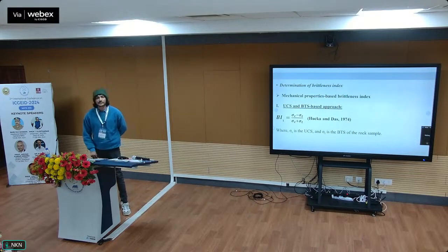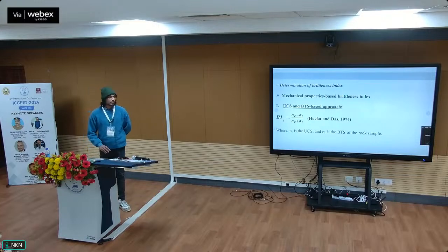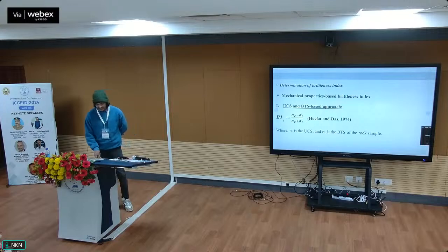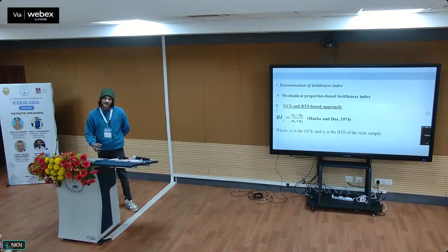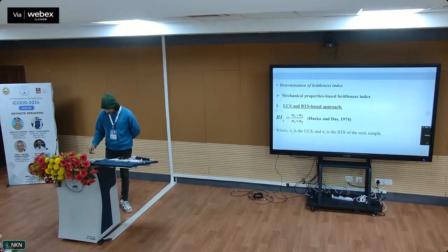We have actually used 6 brittleness indices, and those were broadly separated as mineral-based indices and mechanical-based indices. This is the UCS and BTS-based approach. Basically, we have calculated the uniaxial compressive strength and tensile strength of the samples. Then the ratio of both gives us the brittleness index, because if a sample's UCS is high, then it will be difficult to close the fractures. So more strength will be required to make the fractures close. But if the tensile strength is low, the opposite would happen. So the ratio of both would give us the brittleness index. This is our first index which I have calculated.